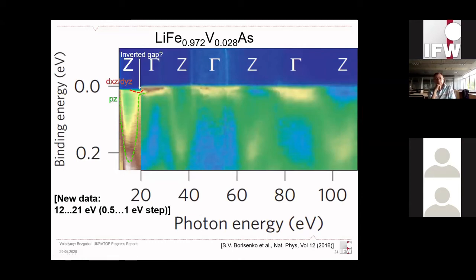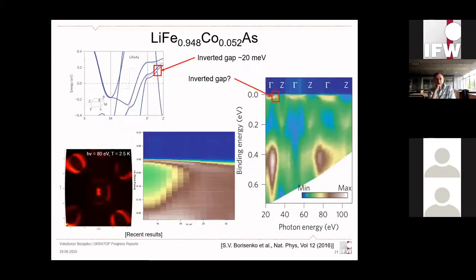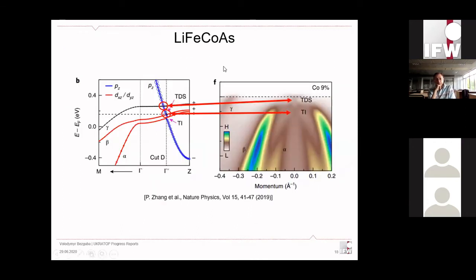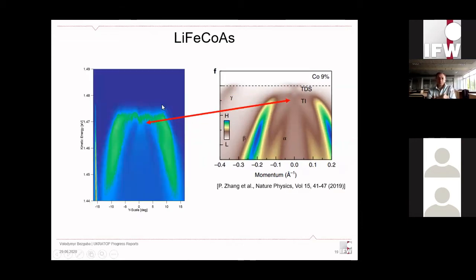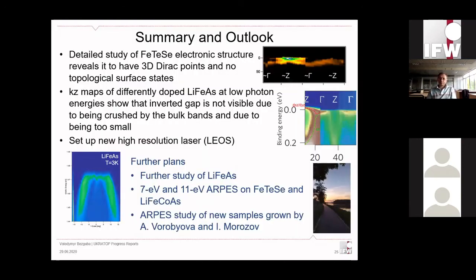To sum up this part, it looks like in their article, the parts they report to be topological surface states is actually, like I showed on this slide, the Dirac cone from the crossing of these bands. And the higher one, which is the topological Dirac metal cone, comes from crossing at gamma. So detailed study of iron, tellurium, and selenium revealed that it does carry 3D Dirac points, but there are no topological surface states there.